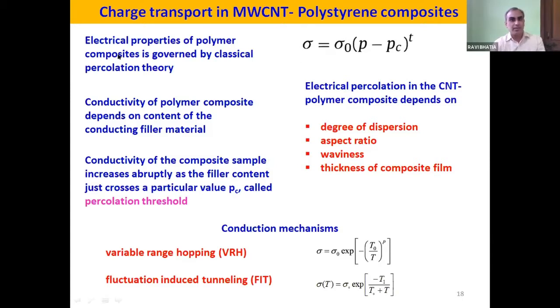For example, the electrical properties of composites follow the percolation theory, and the percolation equation is given as this. Sigma represents the conductivity, P represents the weight fraction or weight percentage of the filler material. For example, if one wants to prepare a 5 weight percent composite sample, 100 mg of the polymer and 5 mg of CNT, it is a rough estimate. Actually, the equation is something else, where we have to take care of the masses of the polymer, masses of the CNTs, and then you divide the mass of filler by the combination of the polymer and filler material, which gives rise to the exact measurement of the weight percent.